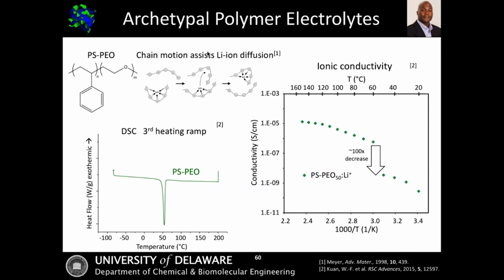It started with polystyrene polyethylene oxide. I've already talked a little bit about that chain motion assisted diffusion, but one of the things I want to illustrate is shown in the right-hand plot on this slide. What you're looking at is conductivity as a function of temperature. You can see that I get reasonable conductivities around 1 × 10⁻⁵, until I get back down to about 60 degrees Celsius, at which point I see a discontinuity in that conductivity.